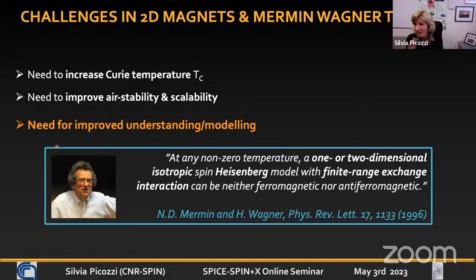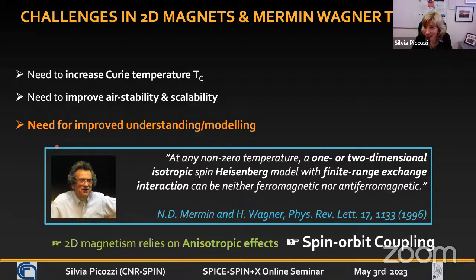And so when one speaks about modeling of 2D magnets, the first thing that comes to our mind is the Mermin-Wagner theorem, which actually says that if your spins are isotropic, so if you have a Heisenberg model, then your 2D magnet will never order. And so to have it order, you need to have some kind of anisotropy. And so this is where spin-orbit coupling actually plays an important role. To achieve a long-range ordering in a 2D magnet, you need to have spin-orbit coupling or some kind of anisotropy in the system.